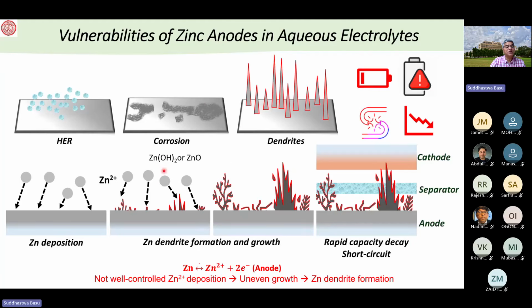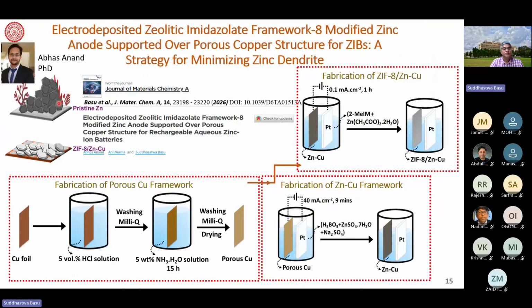Other things are zinc hydroxide and zinc oxide formation, and some oxygen and hydrogen evolution reactions. All these also need to be stopped, and you have the HER reaction as shown here. So our idea, which is published in JMCA, is to have an artificial SEI on the negative electrode which protects, like we have similar things in LIB and SIB, the lithium ion battery and sodium ion battery. We have the same idea for the zinc aqueous battery, where we utilize an artificial layer which works as a solid electrolyte interface, the SEI. Those who are exposed to this term know how much importance is given to SEI formation in a secondary rechargeable battery.